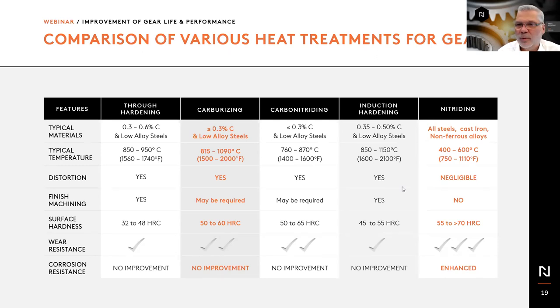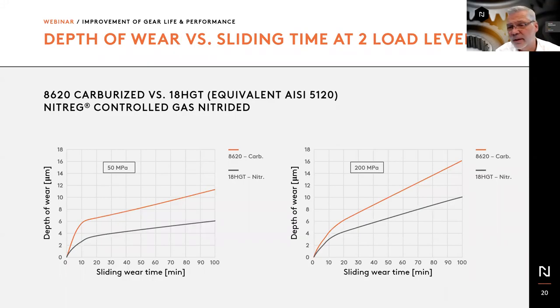The same qualities of case that provide better corrosion resistance also usually provide better lubricant retention, prevent micro welding, and make for a quieter gear. But most gears don't require high corrosion resistance because they are oiled. And going straight from the same point, the chemistry of nitrided layers, with nitrides that improve the toughness and eventually a white layer, provides better lubricant retention as well as good sliding wear resistance. This is